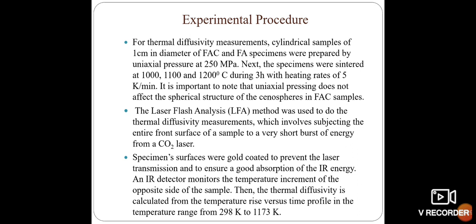For this experiment, the procedure is like this. For thermal diffusivity measurements, cylindrical samples of 1 centimeter in diameter of fly ash cenosphere and fly ash specimens were prepared by uniaxial pressure of about 250 megapascal. Next, the specimens were sintered at 1000, 1100 and 1200 degrees centigrade for 3 hours with heating rates of 5 K per minute. It is important to note that the uniaxial pressure doesn't affect the spherical structure of the cenospheres in FAC samples. FAC is the fly ash cenospheres.